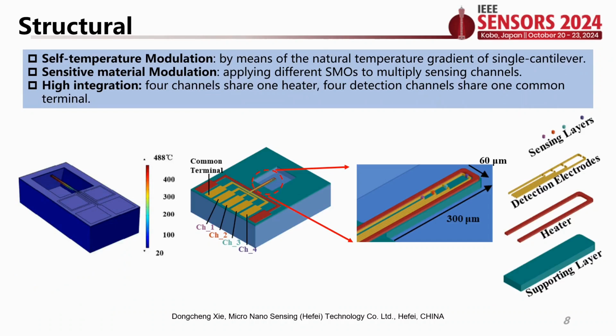In the past, we found that for a single-cantilever micro heater, there is a natural temperature gradient from the fixed end to the free end, as the heat is conducted to the substrate through the fixed end. So if we make several sensing regions at different positions of the cantilever, self temperature modulation can be achieved. And if the sensitive materials in different sensing regions are different, then the material modulation can be achieved at the same time. So in this work, we design a highly integrated 4-channel single-cantilever gas sensor cell,